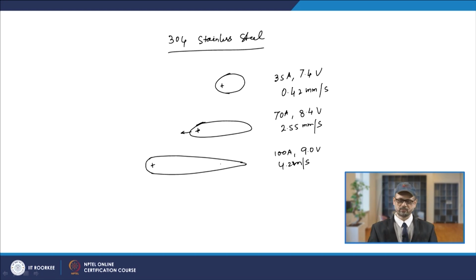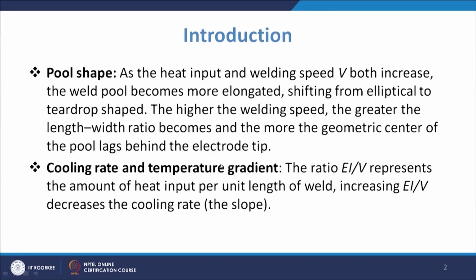Now, there is another curve which will talk about the variation of the cooling rates, and that can be seen. So, that is another effect which is to be understood by us. That is the cooling rate and the temperature gradient. So, this is another important parameter, where we have to understand that the ratio EI upon V represents the amount of heat input per unit length of weld. And if you increase the EI by V, that will decrease the cooling rate.